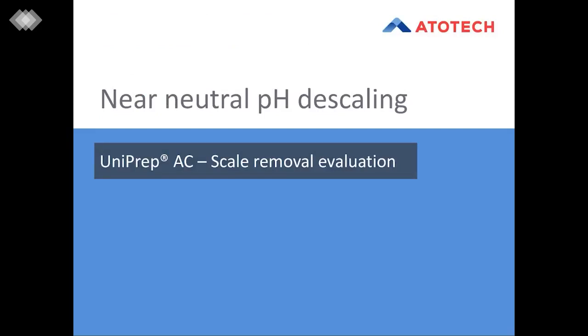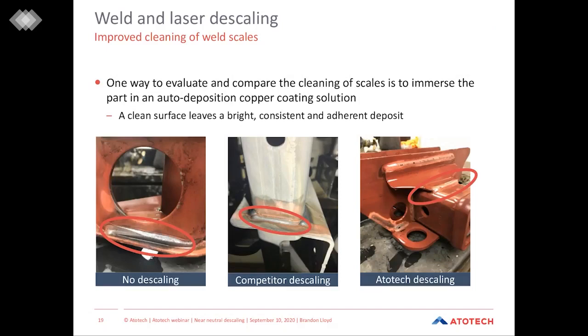So now we'll cover some of the scale removal evaluations so we can see how these processes perform. One way to evaluate and compare the cleaning of scales is to immerse the part in an auto deposition copper coating solution or an electroless copper process. So a clean surface is going to leave a bright, consistent, and adherent deposit of the copper on the part surface.